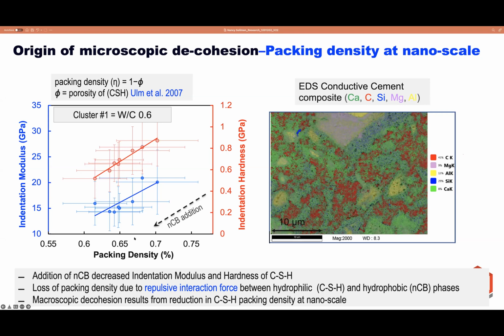And we can conclude from this relation that the addition of nanocarbon black leads to a reduction in indentation hardness and indentation modulus. This reduction results from the reduction in the packing density, which is due to the repulsive interaction force that develops between hydrophilic calcium silicate hydrate and the hydrophobic nanocarbon black phases. And this de-cohesion results from a reduction in packing density of calcium silicate hydrate at nanoscale. This shows an EDS map for the electron conductive cement, which shows that the carbon intermixes very well with the CSH, but the reason for the de-cohesion problem is the loosening of the packing density.